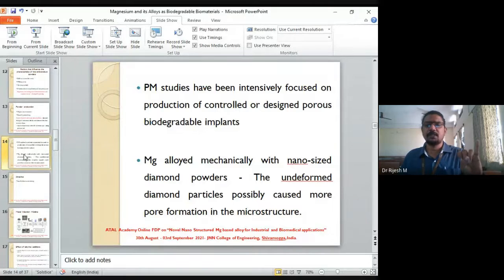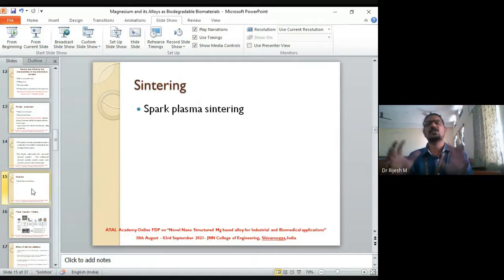Now, controlled porosity is obtained by controlled compression. First step in the powder metallurgical production route is production of powders. Second step is compaction. How much you have to compact depends upon how much porosity you need. How much you have to compact depends upon the initial particle size. Or how much you have to compact depends upon how many interconnecting pores you need. So you engineer it, optimize it, compress it as much as you want, and now you get the product, which is not strong. It becomes strong only if you sinter it.